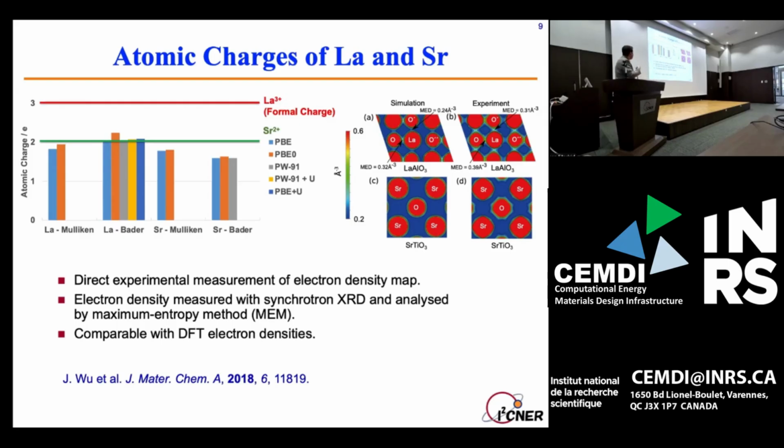So our simulations show that there is a residual electron density at lanthanum. It's making partial covalent bonds. Here I want to stress on partial, not real covalent bonds. Partial covalent bonds with oxygen in the lattice. And when those partial covalent bonds are cleaved on the surface, the residual electron density remains dangling. Orbitals of lanthanum remain with electron density population. And similar to a very poor transition metal, lanthanum actually nicely catalyzes a high temperature oxygen reduction reaction.